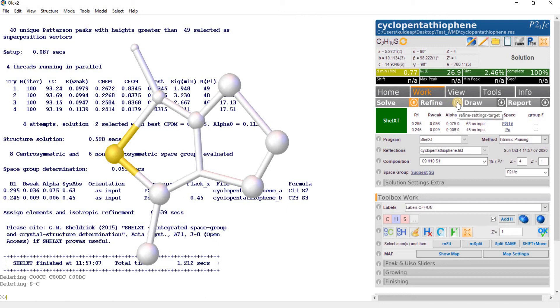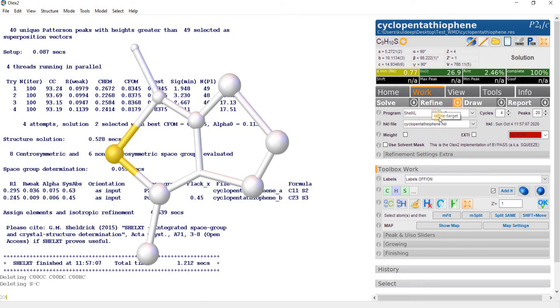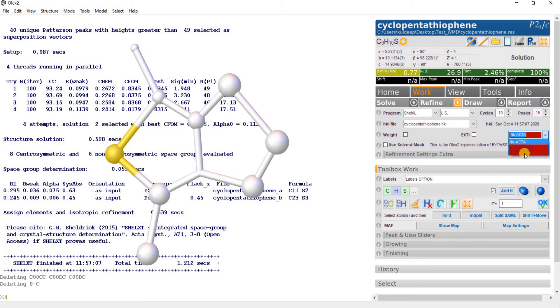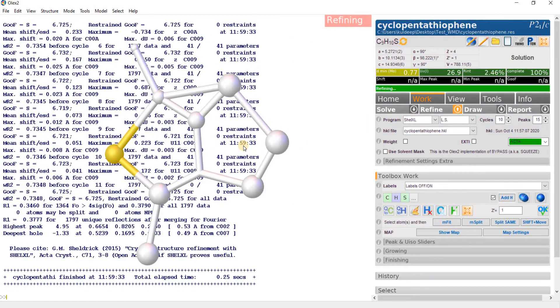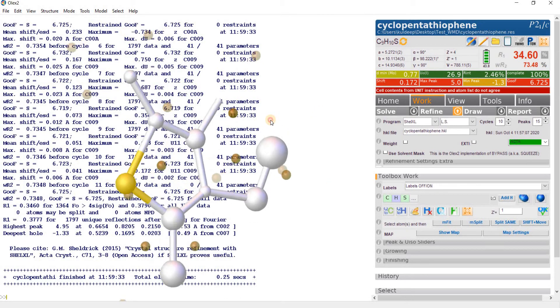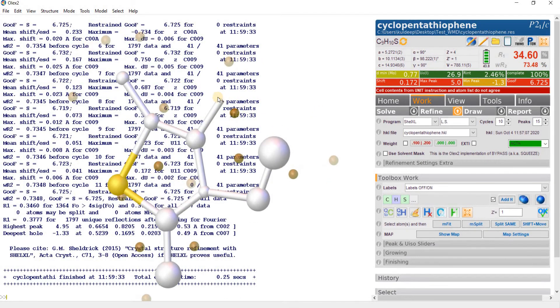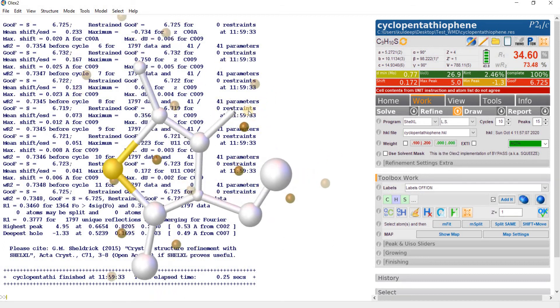First delete these three atoms. Select them, then right click and delete. This bond appears to be an extra bond, let's delete it. And this sulfur should be carbon, so make it carbon. Now compare the molecules with the expected structure. So these are now the same. First refine.